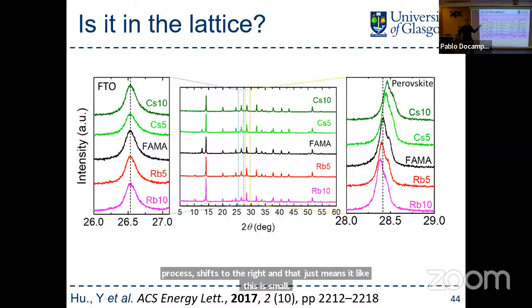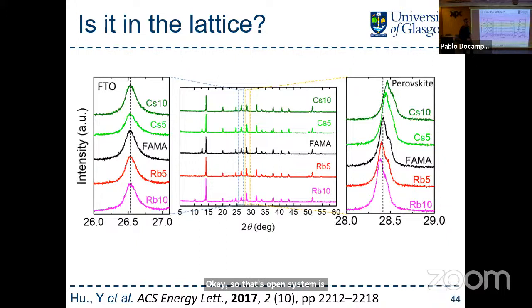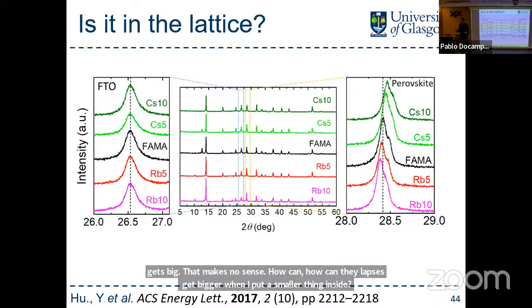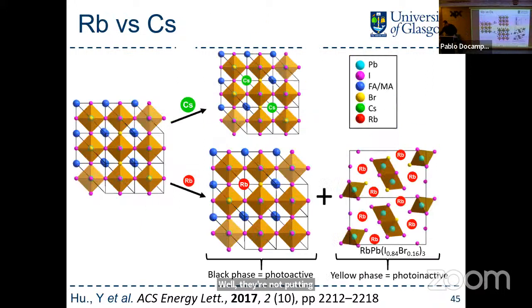Okay, so that's all consistent, which is great. Cesium goes into the structure. You put in rubidium, and it goes the other way. The lattice gets bigger. That makes no sense. How come the lattice gets bigger when I put a smaller thing inside? Well, the obvious answer is we're not putting something inside. What we're doing when we add rubidium is we're taking stuff out.